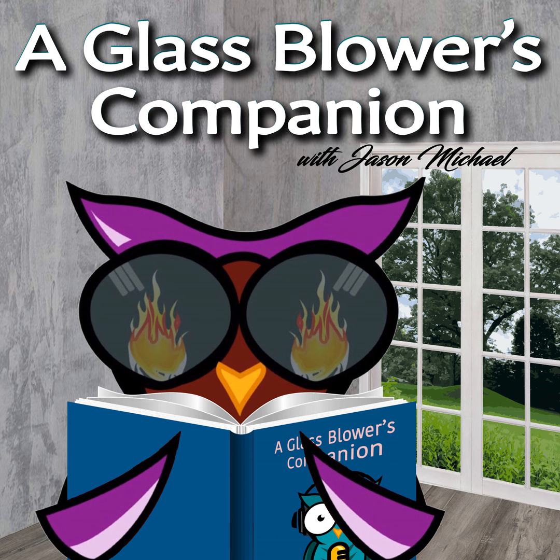Yeah, absolutely. The big thing with the COE, to help anyone who doesn't know, is that soft glass refers to anything that can melt at a much lower temperature, while borosilicate is much more heat resistant, so it has a lower COE, and you need a lot more heat in order to melt it and make it amorphous. Soft glass has always been used because back in the olden days of Murano, Italy, they haven't had the ability to have these crazy oxidized flames that can get up to this high temperature heat. So it just made sense to make this soda lime glass, right? Mm-hmm. It was most popular.